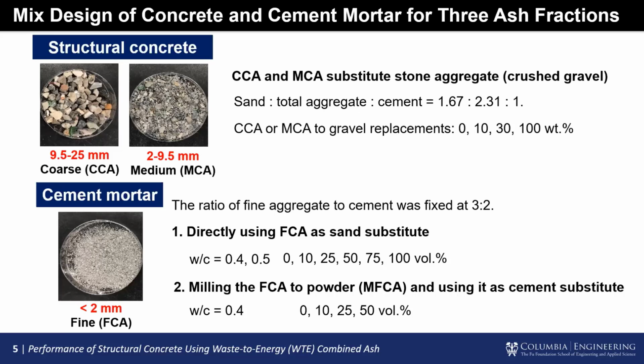So in our study, in all cement mortars, volume replacement is conducted in our mix design. When the fine combined ash is used as a sand substitute, the replacement is up to 100 volume percentage. And when it is ground to powder, the replacement is up to 50 volume percentage.